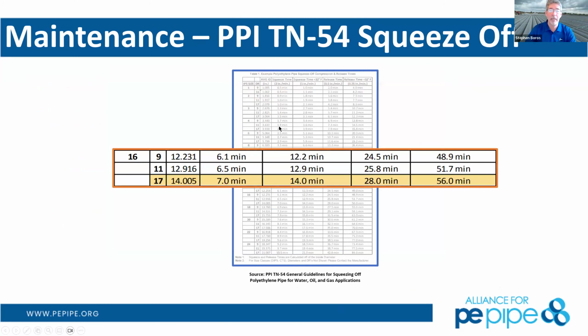So, for example, within this document, TN-54, it's going to tell you for every size pipe what the proper parameters are. Let's look at 16-inch DR9, pretty heavy wall pipe. That's going to have an ID of 12.2 inches. Your squeeze rate, bringing those two bars together, is going to be 2 inches per minute, the recommended value. And it's going to take you 6.1 minutes to squeeze that pipe totally closed with the proper amount of wall compression. If you're below 32 degrees, that time's going to double. Now your squeeze-off rate is only 1 inch per minute.